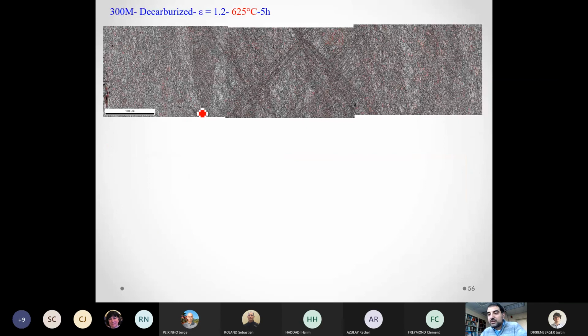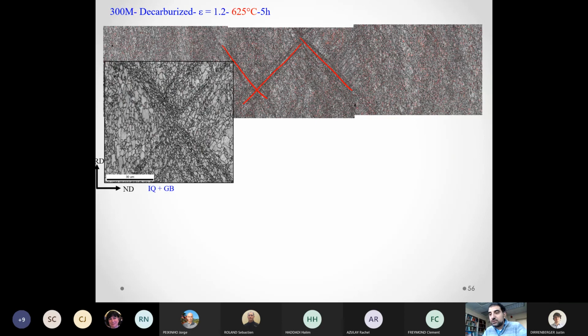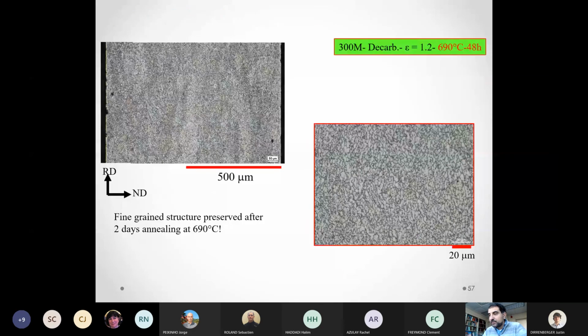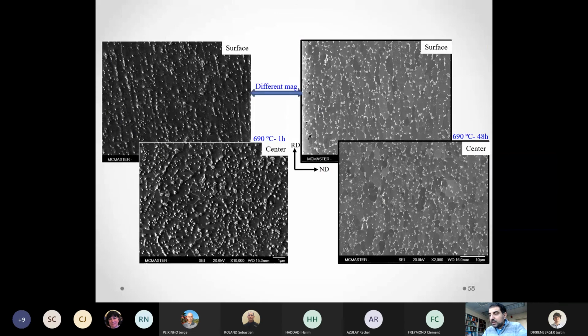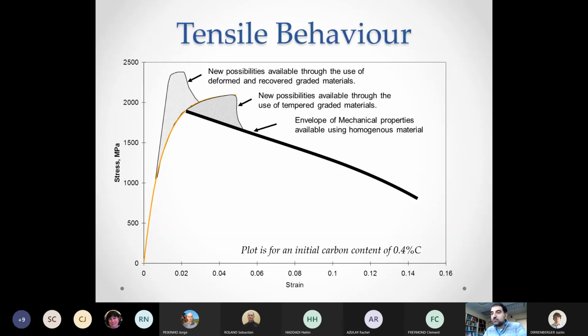Although the material has now completely recrystallized, you still see the ghost or the evidence of the previous shear bands. The reason for that is the grains within the shear bands are smaller, they're finer than the grains outside the shear band. So we can use decarburization as an intermediate step to create these mixed-mode grain size distributions. And this is an example just zooming in on one of these regions, and you can see the extremely fine grains within the shear bands and then the larger grains outside the shear bands. And the longer, of course, we keep the sample at high temperature, the more uniform the microstructure will become, and we can even completely normalize the carbon profile at long times.